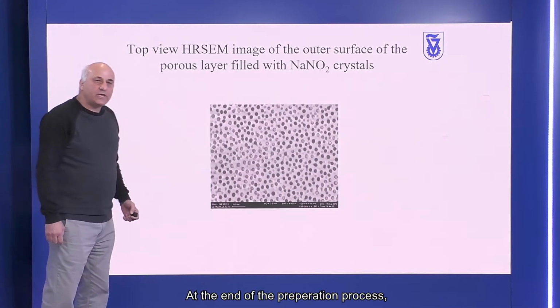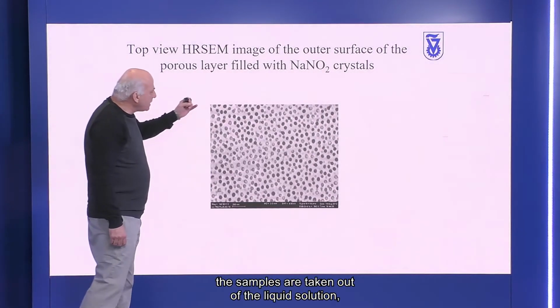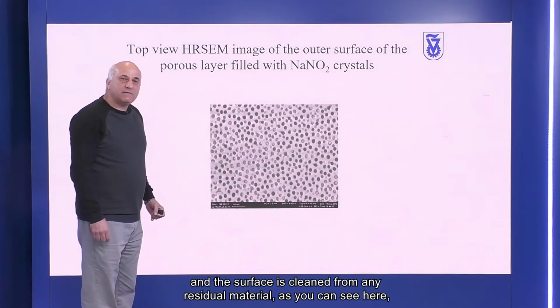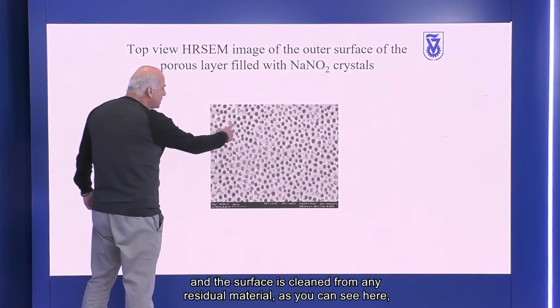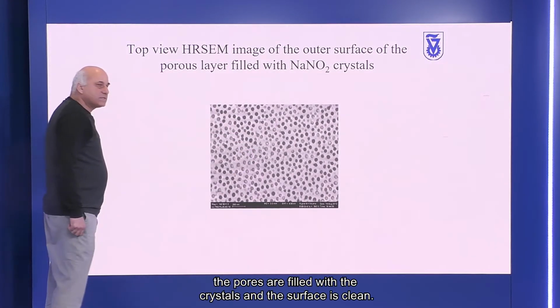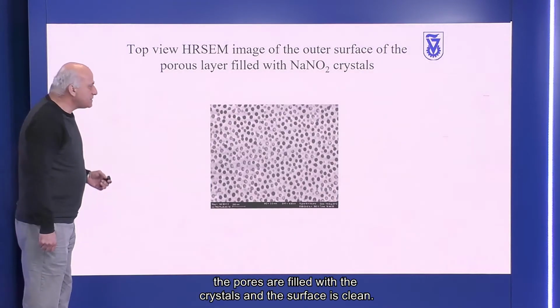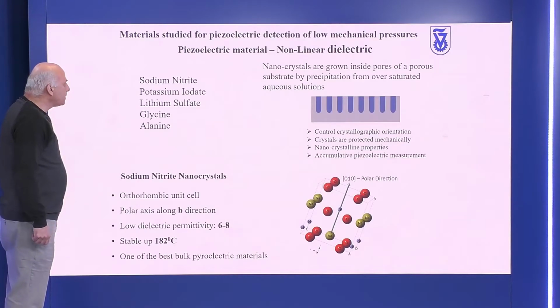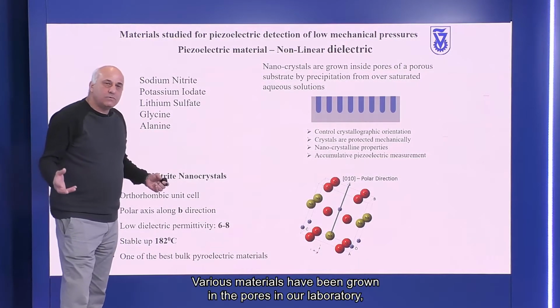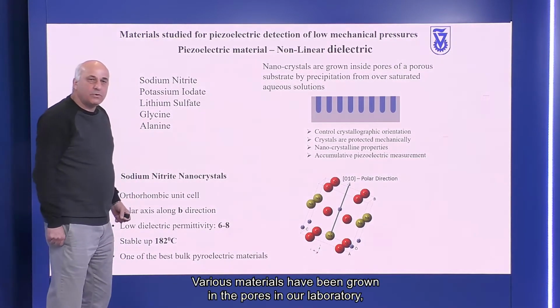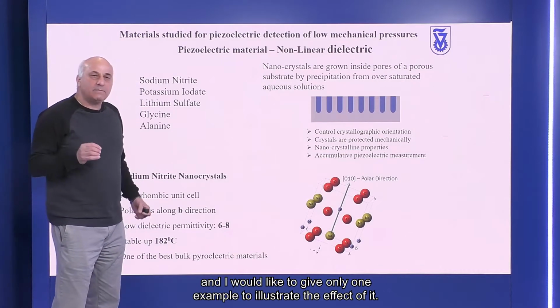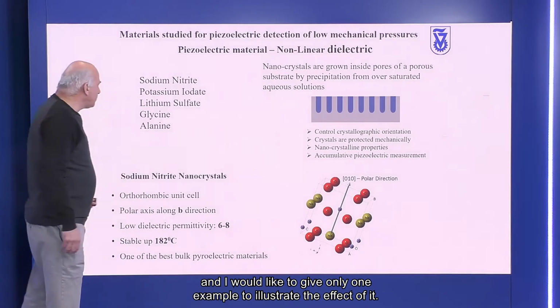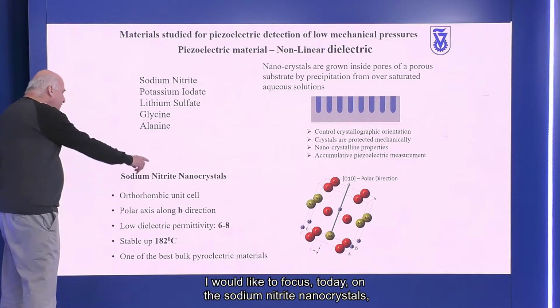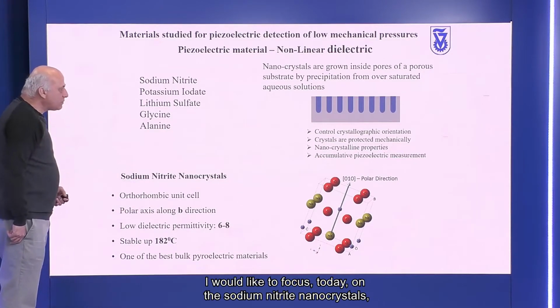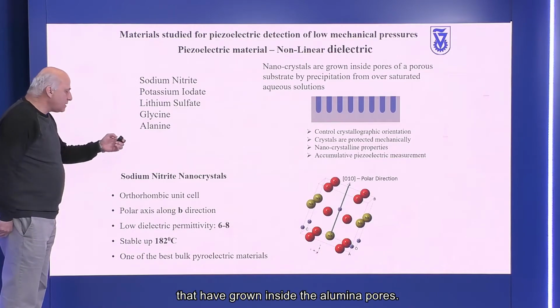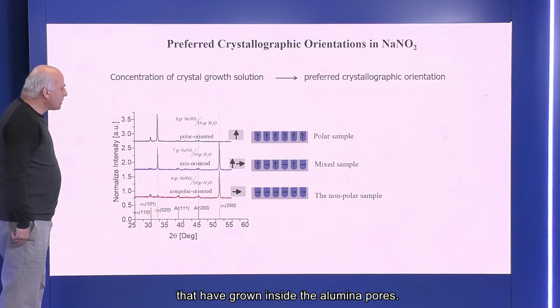At the end of the preparation process, the samples are taken out of the liquid solution and the surface is cleaned from any residual material. As you can see here, the pores are filled with the crystals and the surface is clean. Various materials have been grown in the pores in our laboratory, and I would like to give only one example to illustrate the effect. I would like to focus today on the sodium nitrite nanocrystals that have grown inside the alumina pores.